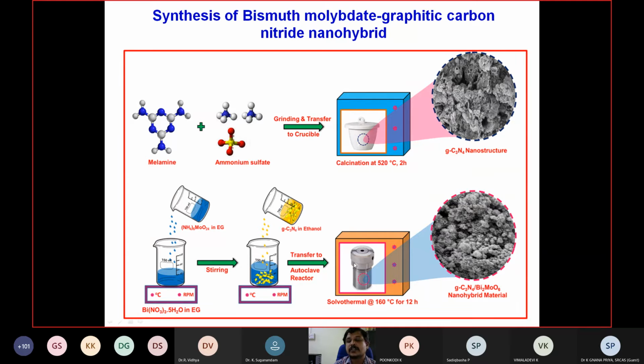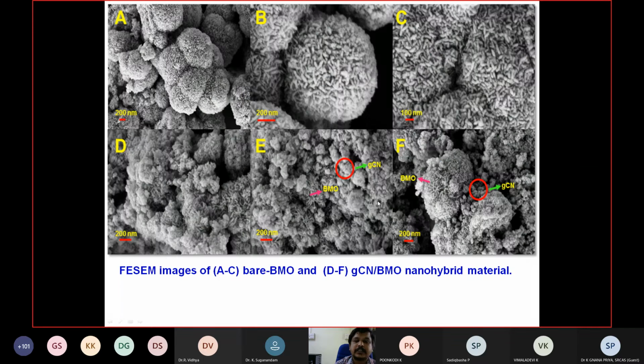Then it will be subject to the solvothermal treatment. Finally, we get a hierarchical structure of this heterojunction, the graphitic carbon nitride bismuth molybdate heterojunction. These are the morphological studies: the FESEM images of bismuth molybdate, the single component. This FESEM image shows the heterojunction after forming with graphitic carbon nitride. The hierarchical structure is still maintained and the graphitic carbon nitride is spread over the bismuth molybdate.